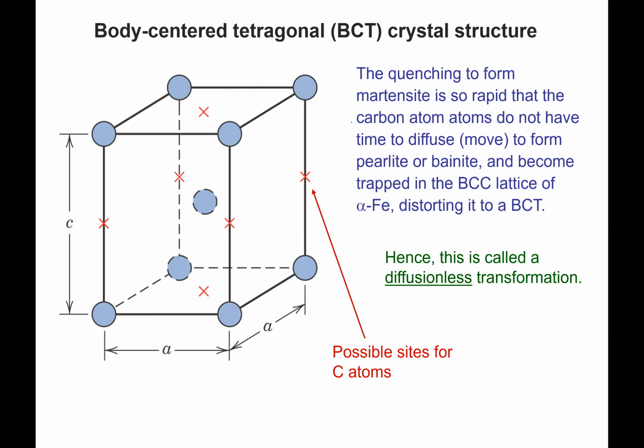And then when we shift down into this Martensite, it transforms into body-centered tetragonal. So remember that tetragonal means that I stretch one axis. And so this stretched axis is the location where the carbons can sit, so I can fit more carbons in the lattice. But they're in there and they stretch that C axis, forming body-centered tetragonal.